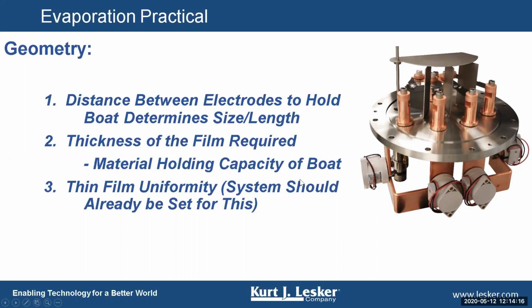It's also important to estimate how much material a boat or a crucible can hold, because that's intimately tied to how thick of a film you can make ultimately. The thin film uniformity is also affected by the position of these evaporation sources in relation to the substrate. This should already be set though in any system that you're currently using, and it should have been designed so that you get relatively good uniformity.